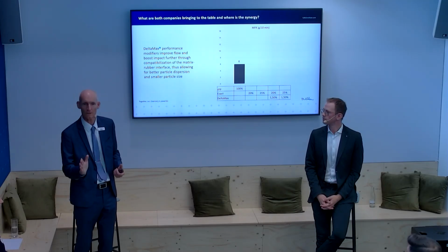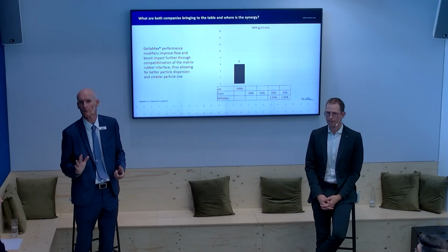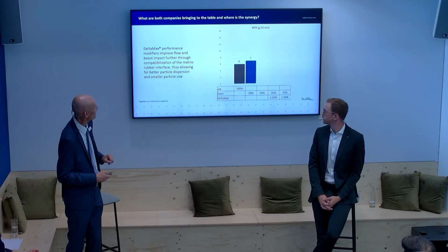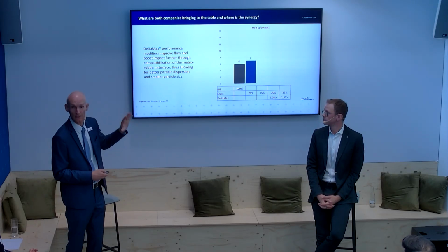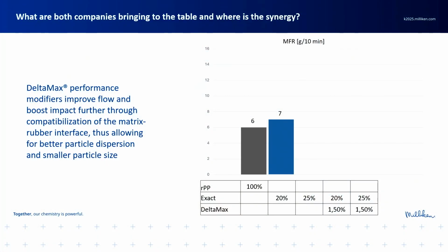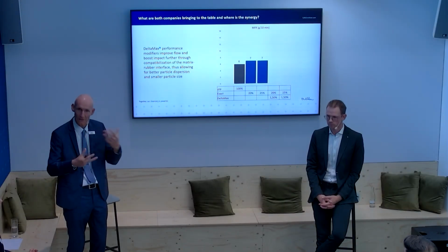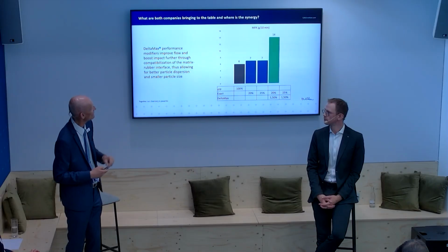Well, you need good materials in the blend. You can think about, well, let me work on productivity. Because you know in automotive, productivity, the takt rate, is very, very important. And that is exactly what Delta Max brings you in this synergy with Exact Plastomer. Here we talk about melt flow rate, and melt flow rate is productivity, is speed in injection molding. When we add Exact, we don't really change the melt flow rate. The grade has a similar type of flow properties, and blends well with the polypropylene. So we have a good blend, and now we need to accelerate that, and that is going to drop my cost again. And I'm going to do that with Delta Max.